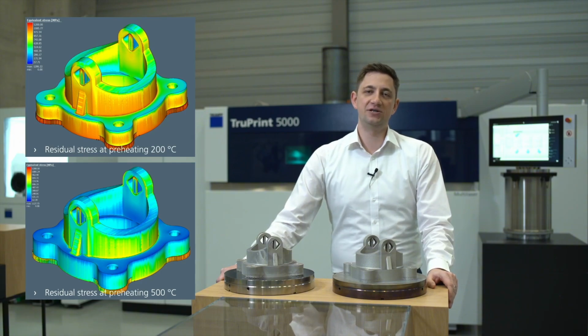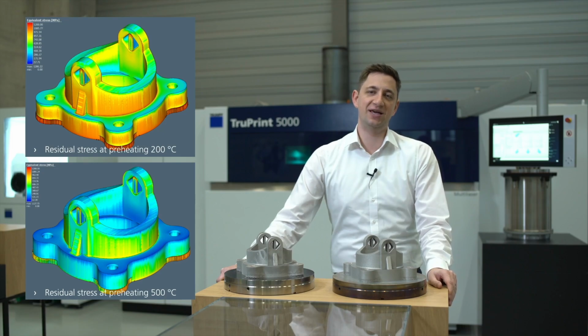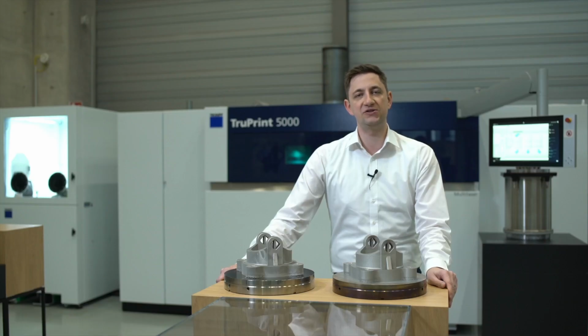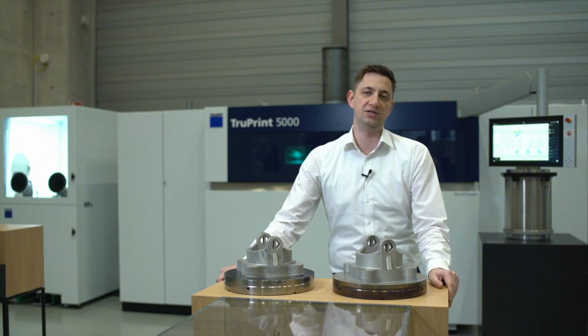It is so significant that the values for the part preheated with 200 degree exceed the mechanical properties of the material. That is what leads to the damage of the support structures or cracking of the part itself. This sample shows clearly how you can improve your 3D printing results for aerospace applications by using 500 degree preheating.